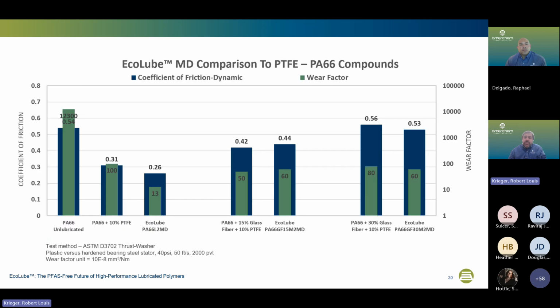So here's some data comparing PTFE and EcoLube containing PA66 compounds. On the left, you see 3 PA66 items. The middle contains 2 15% glass-filled PA66 items, and the right contains 2 30% glass-filled PA66 items. In each, we're comparing 10% PTFE as the control and our EcoLube offering in each glass loading. And we have an unlubricated, unfilled PA66 as well.